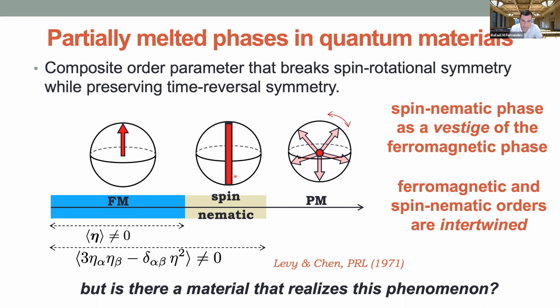In this regard, the spin nematic phase is a vestige of the ferromagnetic phase. We can say that these two phases are intertwined because one order parameter is the composite of the primary one. Already, 50 years ago, in this paper, the authors proposed a model that realizes this sequence of phases. Of course, the question is whether there's a material that realizes this phenomenon. This is a very active area of research.